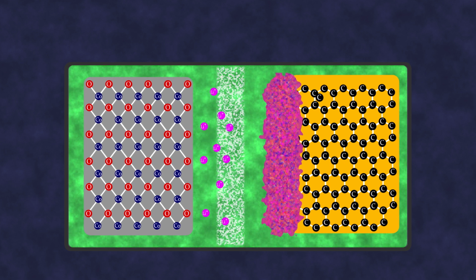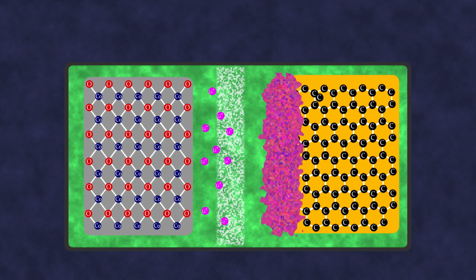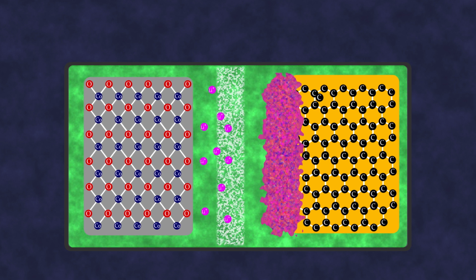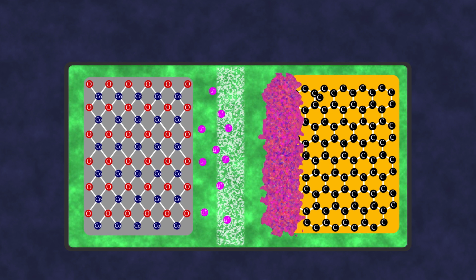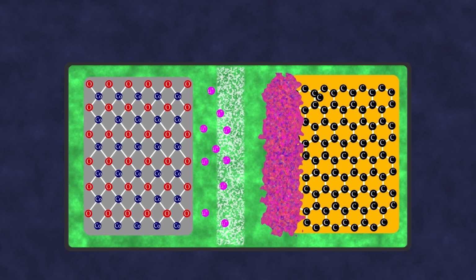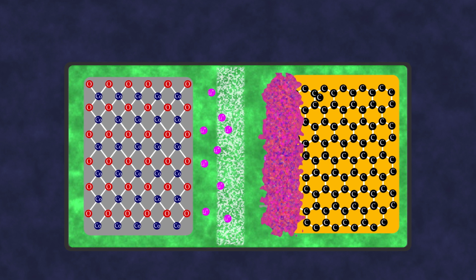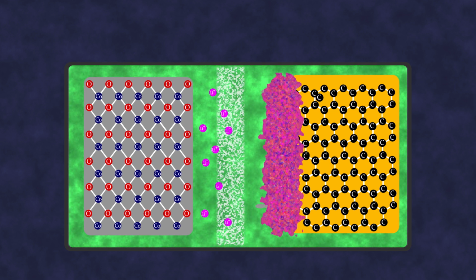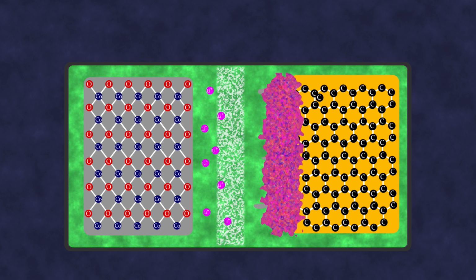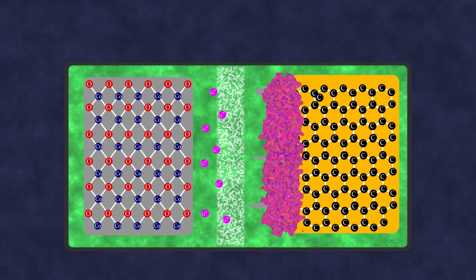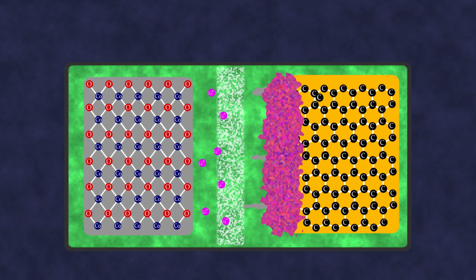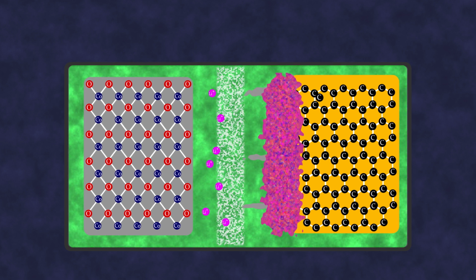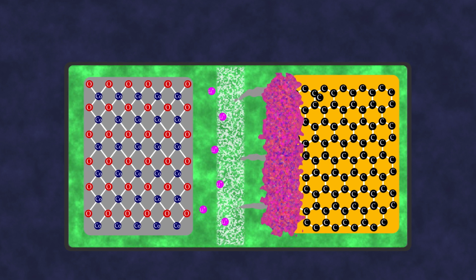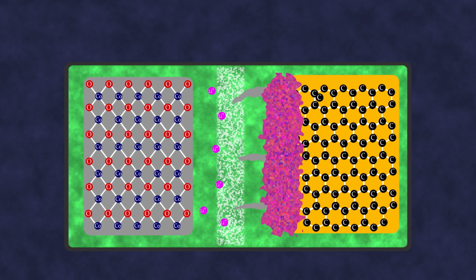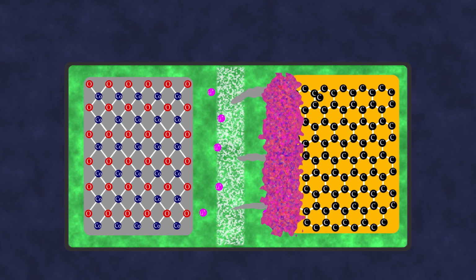As the layer thickens, its permeability may decrease to the point where lithium ions can no longer pass through it, forming deposits of pure metallic lithium outside the layer. These deposits are also known as dendrites. Not only does the metallic lithium in dendrites no longer participate in the battery's operation, reducing its capacity, but worse, dendrites can puncture the separator, causing a short circuit, fire, and explosion, even in a previously functional battery.